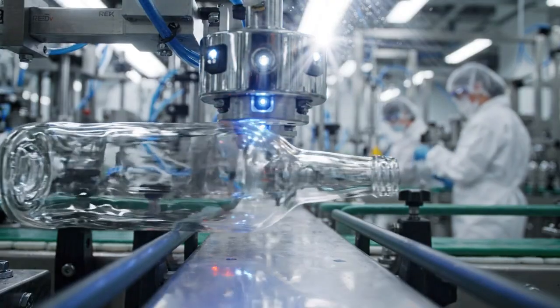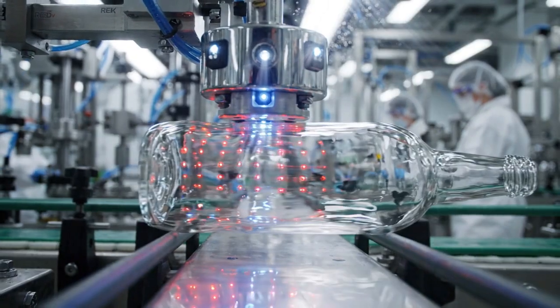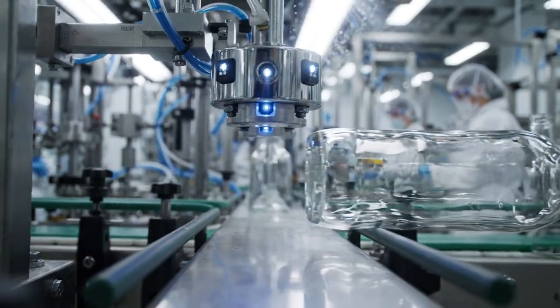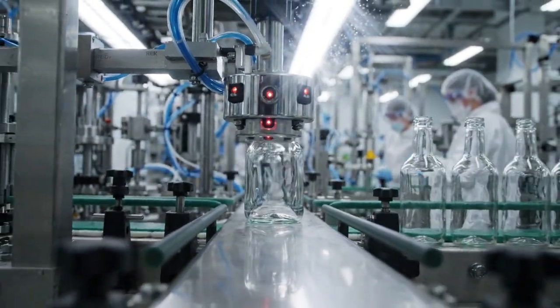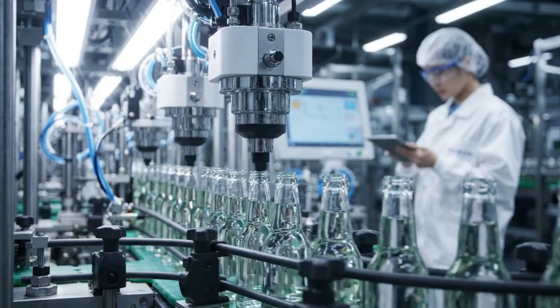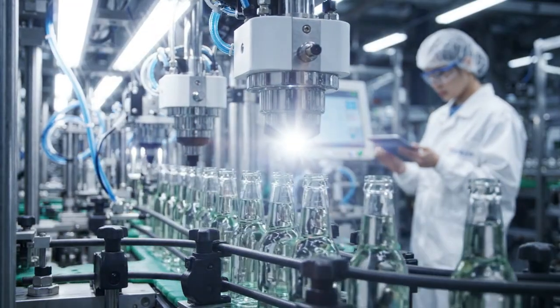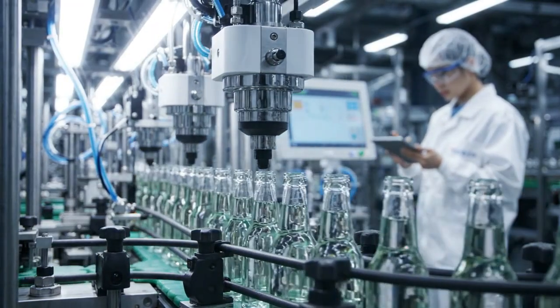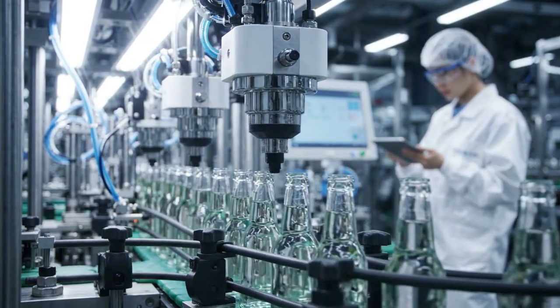Base defects are particularly dangerous. A crack in the bottle base can cause catastrophic failure when the bottle is filled with hot liquid or pressurized with carbonation. Finish defects cause seal failures. A chipped or cracked sealing surface allows leakage, contamination, or loss of carbonation pressure in beverage bottles.